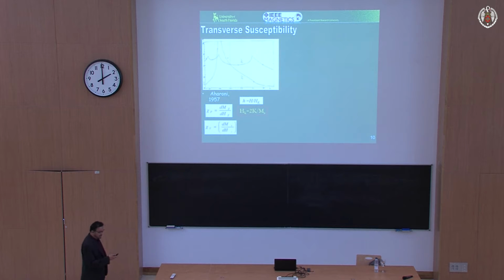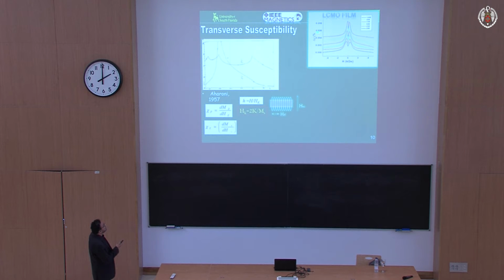So if we can set up a geometry to measure the transverse susceptibility, which is exactly what we did in our experiment, we can measure peaks, and we've been seeing these peaks for more than 15 years now on many, many different systems, and we can characterize them, we can extract the anisotropy constants and everything, okay? Very reliable. So for example, here's a lanthanum calcium manganate film, well-defined directions, so the peaks are sharp. We can read off the HK values, the anisotropy peaks, and then we can extract the anisotropy energy, okay?